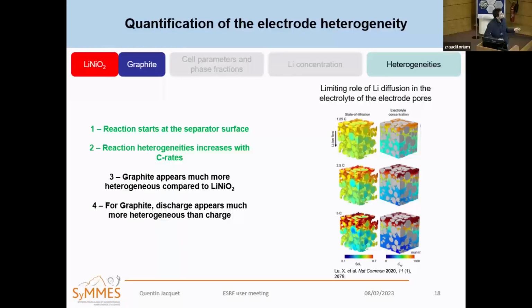This is a simulation of a lithiation on the real electrode structure, and you can see here the lithium concentration in the solid phase and here in the liquid phase. And it's well known that at high C rates, you're limited by the lithium diffusion in the electrolyte phase, which basically means that you have less lithium in the electrolyte at the bottom of the electrode, and hence your reaction is limited at the bottom of the electrode because of that.